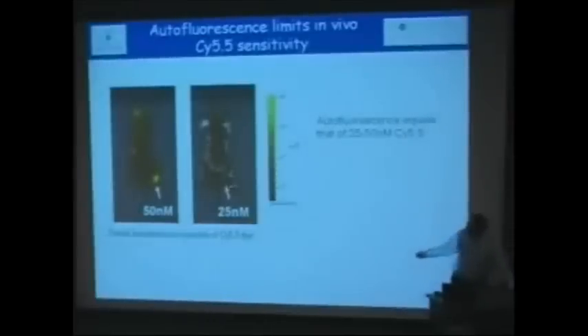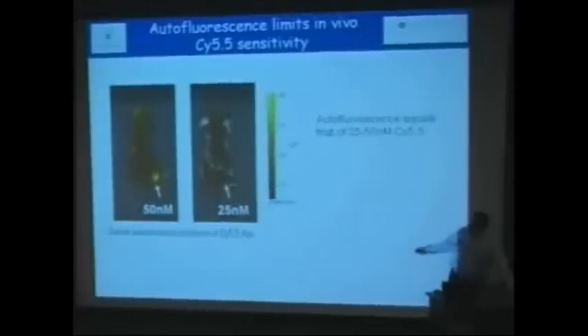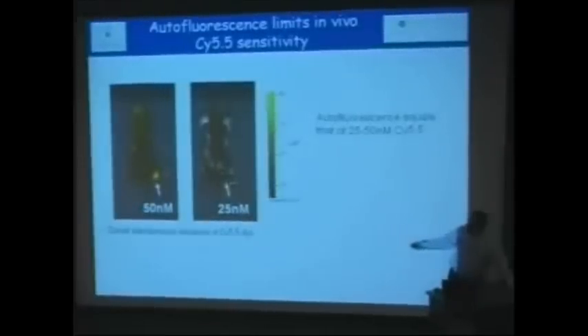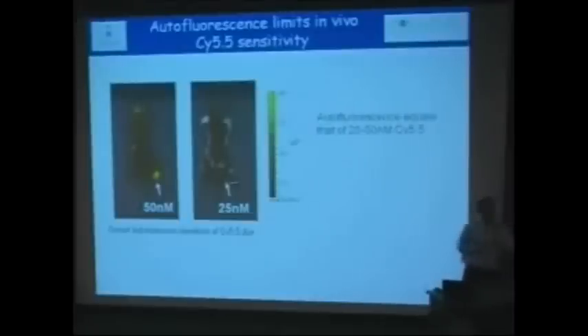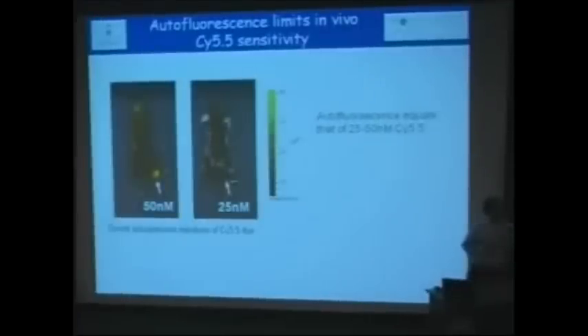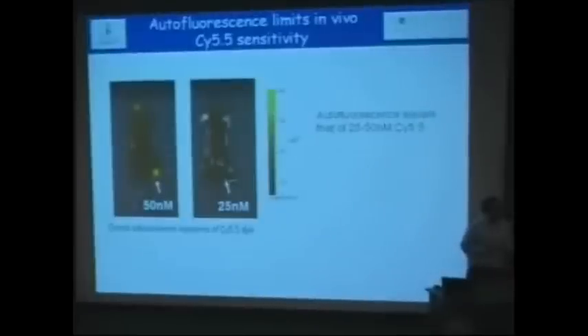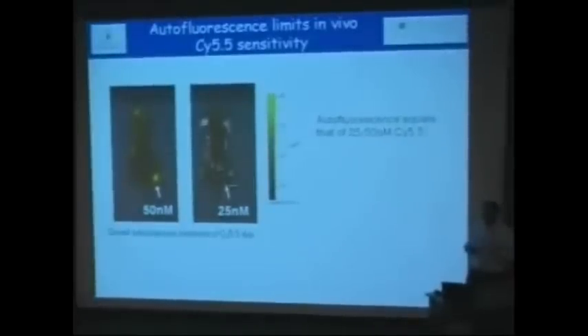You can see that if you inject a dye with a concentration of 50 nanomolar, you can see it. But if you inject about 25 nanomolar, you can barely see it. So the biology and the autofluorescence at the wavelength that we work with, where the biologists like to work, is limiting the sensitivity inside the body to about 25 nanomolar or so, which is again a biology-driven issue.